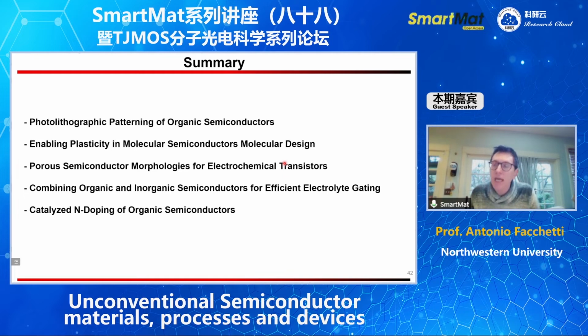This can be important if the polymer is very textured and/or hydrophobic. If you're using a polymer which is hydrophilic, it is not that important. Also, I showed you that we can combine organic and inorganic semiconductors to create efficient electrolyte gating. And finally, I showed very briefly an example of using a catalyst to enhance the efficiency and the conductivity of n-doped organic semiconductors.